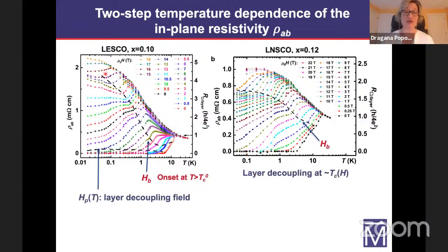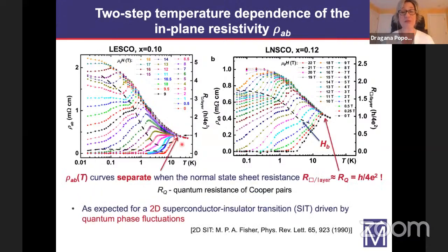So what this means is that almost all of the data shown on these two plots are describing the 2D physics, the physics of copper oxygen planes. An interesting piece of evidence that supports this conclusion is the fact that these curves separate into two families. One family that wants to become superconducting, another one that does not, exactly when the sheet resistance is basically the same as h/4e squared, which is the quantum resistance of Cooper pairs. And this is precisely what you would expect for a 2D superconductor-insulator transition that is driven by quantum phase